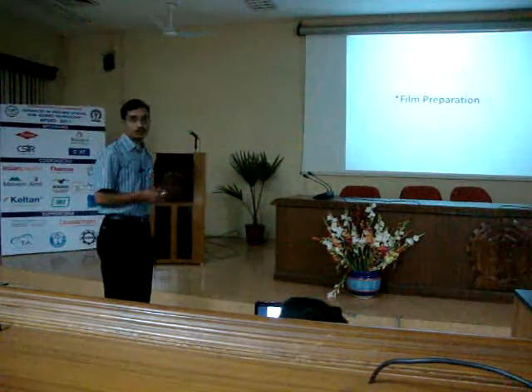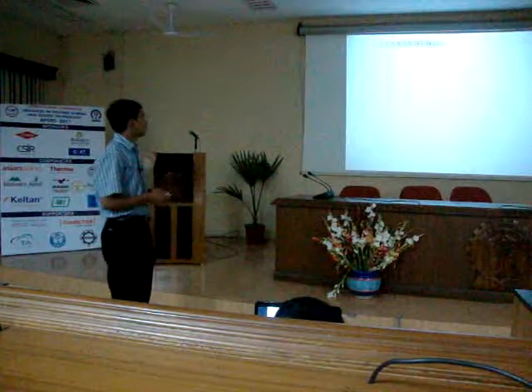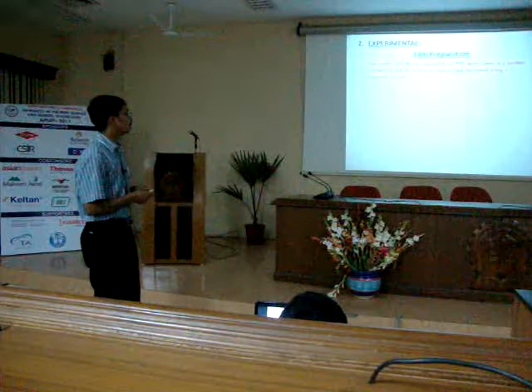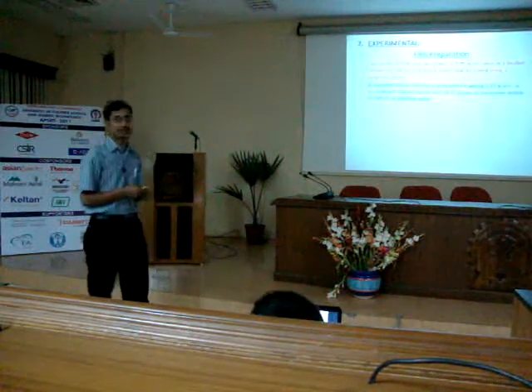So in the experimental section, first of all I will talk about the film preparation. First of all, 2 grams of PVA and 2 grams of PVP were taken in a beaker containing 100 ml of distilled water and dissolved using a magnetic stirrer. A standard iodine solution is prepared by adding 1.27 grams of resublimed iodine crystals and 16.67 grams of potassium iodide to 100 ml of distilled water.